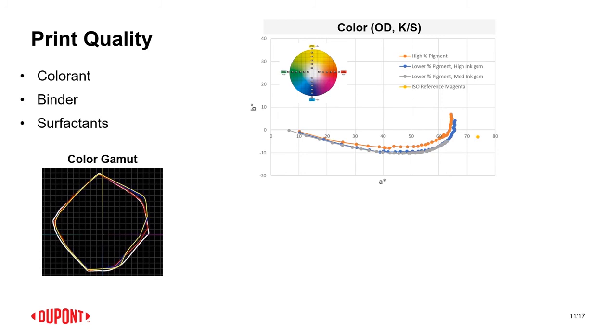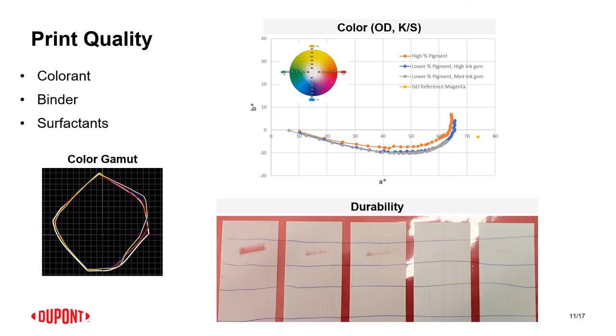And then finally, here, just wanted to talk about durability. So what you're looking at here is a sample of our white ink on a film, right? And so basically, you can see, right, this was just an evolution of some of the work that we've done, but you can achieve a good optical density with a white pigment ink on film. But then you have the challenges, right? Ultimately, people that are looking at pigment inks on film ideally don't want to have to overprint it. And so you can play with some of the knobs, like your binder selections, to be able to improve your overall durability so that you don't smudge or scratch it as easily.